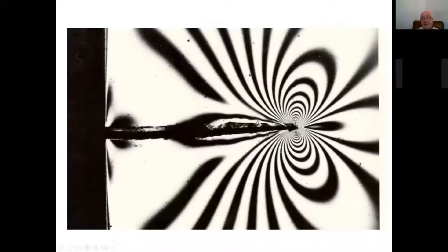Now, if you have cracks in such a loading situation, when you have many of them, you may have another problem. As you can see, around the tip of the crack the region is quite blurred. So this is the process zone. You cannot see too many of these fringes. This is an issue which will complicate measurements in some situations.